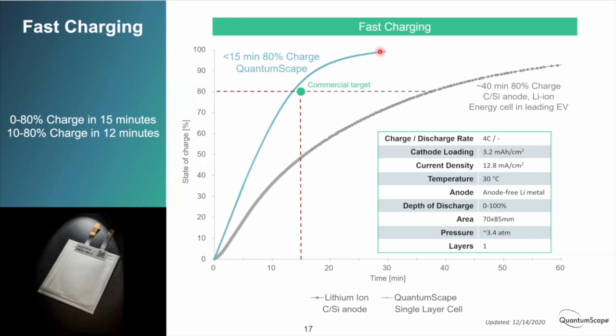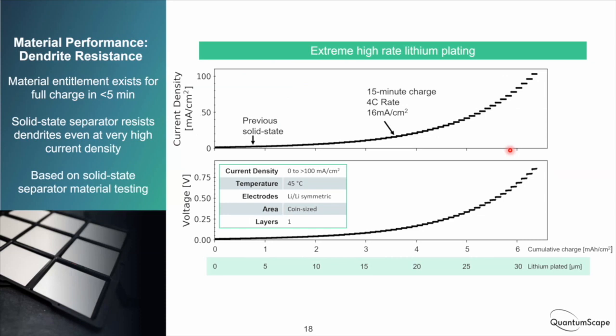So this cell was again the same cell that I described on the last slide in terms of cathode loading, temperature, anode area, pressure, number of layers, and so forth. So it's the same cell that can do fast charge. Then we wanted to really test dendrite resistance of the separator itself. So we took the separator out of a cell and did a stress test where we just increased the current density and saw at what current density the separator could withstand.